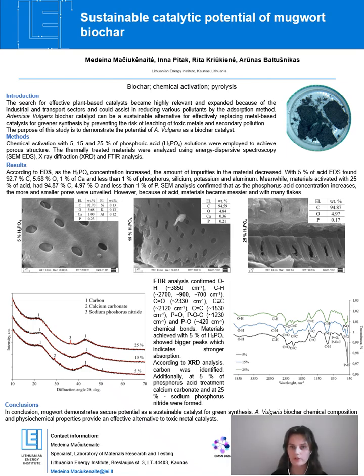Activated biocarbon is produced through additional activation processes that enhance pore development, surface area, and the number of active adsorption sites. Activation can be performed using physical methods such as steam or carbon dioxide treatment or chemical agents, including phosphoric acid, potassium hydroxide, zinc chloride, and other activating compounds.